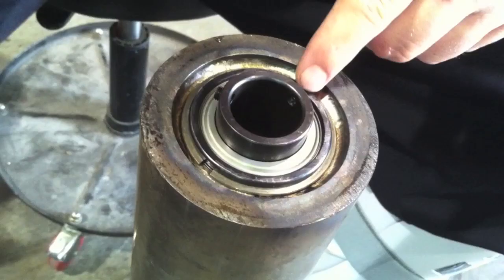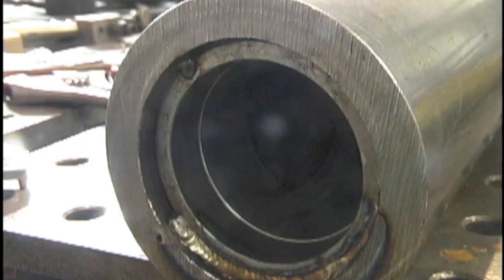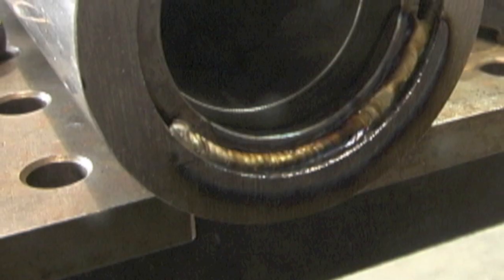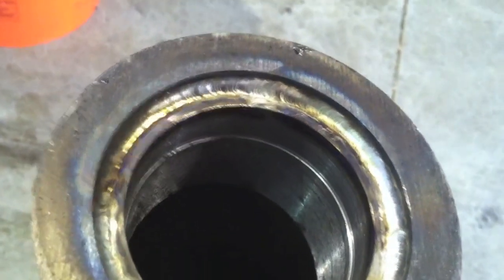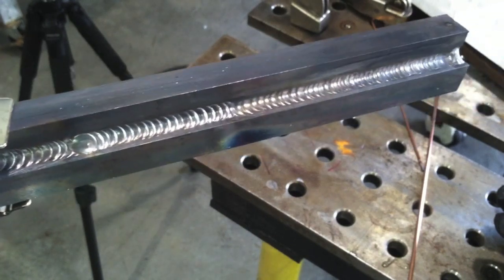There are issues about preheat and hardening and being brittle if you're not careful, but for the sake of just this video I didn't preheat anything. Here is the practical application that we came in the shop, a bearing sleeve pressed in a big piece of heavy wall tubing, it's a roller. We heated it up to get a shrink fit and it went in too far and we had to beat it back out from the other end, but it just needed to be recessed about a quarter inch past flush. The weld here is such a tight fit after that thing shrunk and cooled off that I didn't want to risk shrinking it anymore with heavy weld, so I just put one pass, again using the Everlast 210 EXT here, no pulse, probably only about 150 amps, just trying to get one little nice-looking pass in there. I was walking the cup on that because that thing was so hot from it being preheated. There it is with the bearing in there, here is the single pass side of that 4140 joint and there is with two passes, about a half inch thick material.